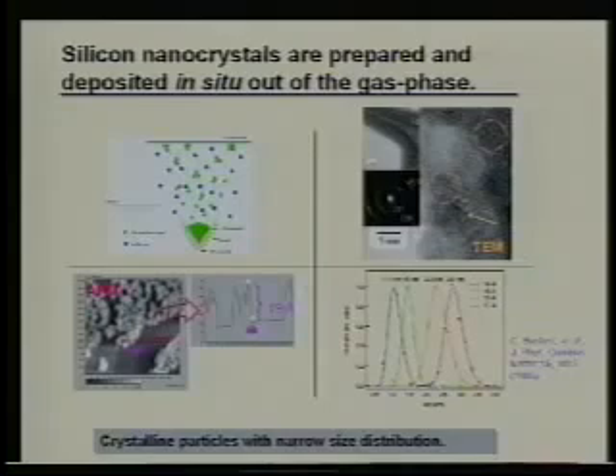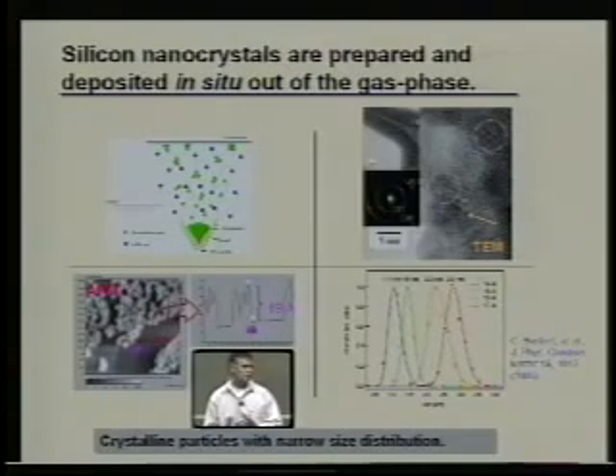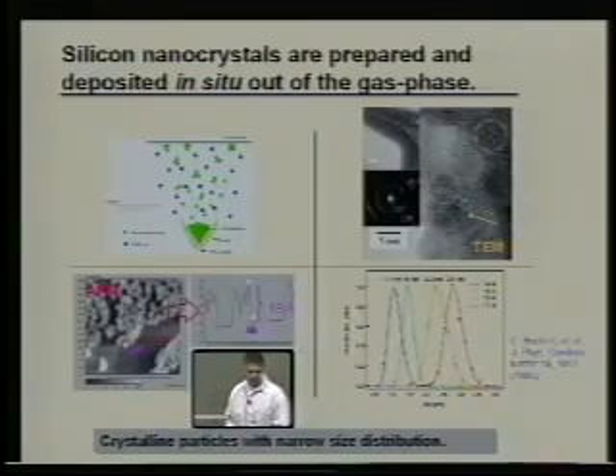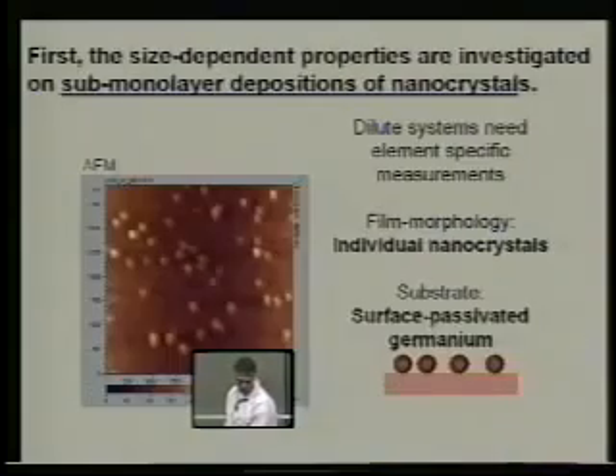So our group is actually mostly interested in group 4 nanomaterials, silicon and germanium. And we grow these out of the gas phase, so we have an evaporator. And we evaporate material into the gas phase. There's a buffer gas. You get a supersaturation. It condenses, much like raindrops condense in a cloud, and you can put them on a substrate. And we do various techniques of proving the crystallinity and size, AFM, and we get reasonable size distributions out.